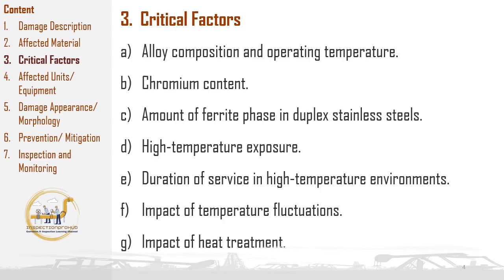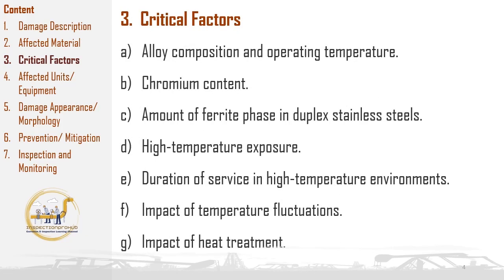Fifth critical factor is the duration of service in high-temperature environments. The duration of service in high-temperature environments is a crucial factor in the embrittlement of materials, as prolonged exposure to elevated temperatures can lead to significant degradation over time. In practical terms, materials exposed to temperatures ranging from 600 to 1000 degrees Fahrenheit for extended periods, typically over many years of service, are generally considered to have been affected by embrittlement.